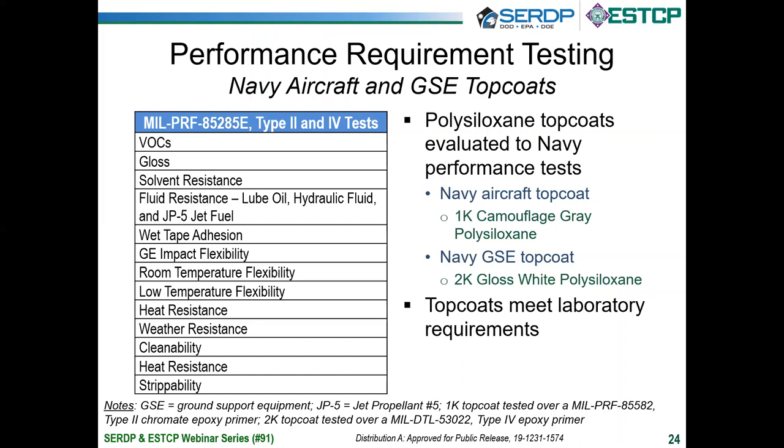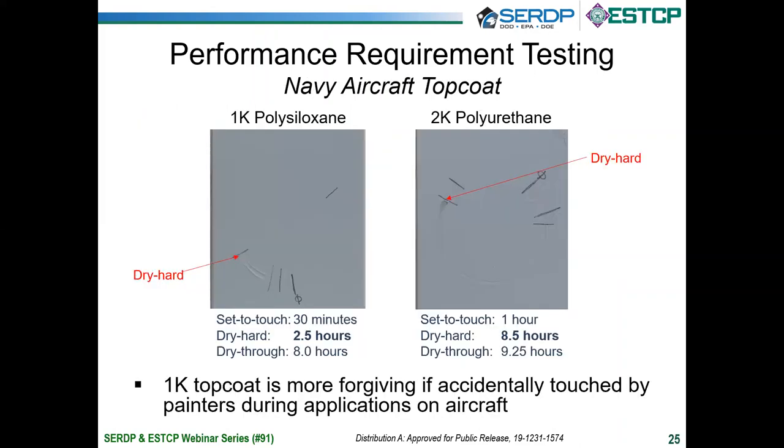Okay, slide 25. Okay, another unique attribute of the polysiloxane top coat, at least of the single component polysiloxane top coat, that is worth noting, is that it does have a faster dry time than the two component polyurethanes. The reason why this is important is that specifically when you're painting aircraft such as helicopters that have a lot of protrusions on them, and the artisans have to delicately move around the aircraft and they're crawling under the aircraft and so on, they've noted that the single component top coat is more forgiving because it cures